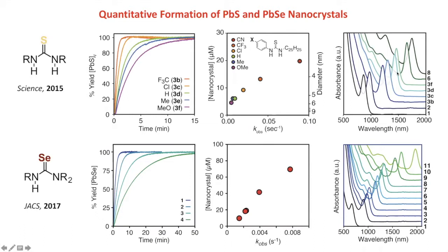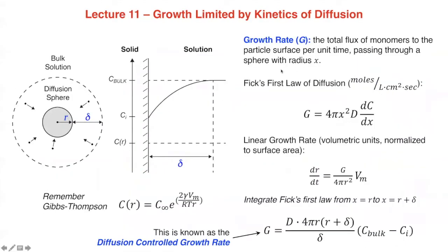So last time we talked about how precursors, these thio and selenourea compounds, their reaction kinetics, how fast they break down into solutes, can control the number of particles. And this is something that was anticipated by Sugimoto and formalized by him in his mass balance equation. And that's been thoroughly demonstrated now on a variety of different metal chalcogenides. There are also examples in other material systems. And we talked about different growth